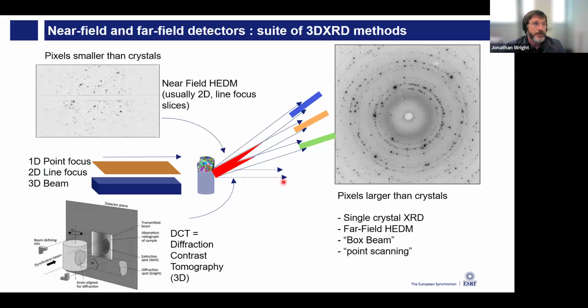So now if I come on to the 3D XRD methods and the grain mapping methods to try to give more of an idea, we come into the sample usually with a bigger X-ray beam size. And when we have these near field detectors, the detector slots in very closely behind the sample. And the position and shape of the diffraction spot on the detector depends on where the grain is inside the sample. When we have these far field detectors, the detector's very far back, and the position of the spot on the detector depends just on the scattering angles. So just on the internal chemical crystallography and unit cell. And by putting these two things together, the idea is to get a complete picture of what happens inside the sample.